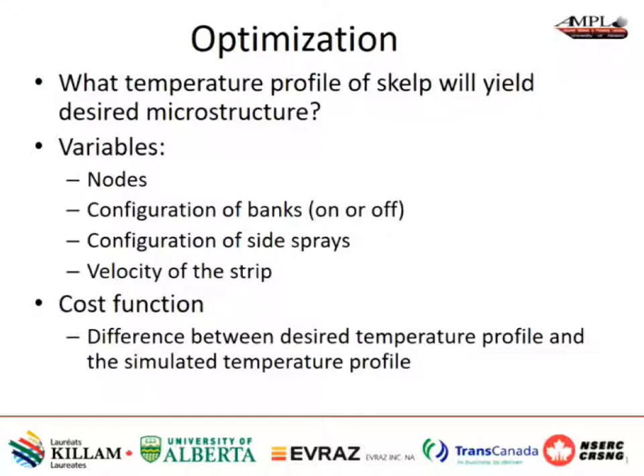be looking at, what should you be doing with side sprays, because every time there's a bank of water that comes down before the next bank, they blow air to get rid of any residual water or steam on the surface. So what should that configuration be, and how do you vary the velocity of the strip? The cost function for optimization is essentially the difference between the desired temperature profile that you want to go through in the CCT diagram to one that you actually obtain from the various configurations that you set in the model.